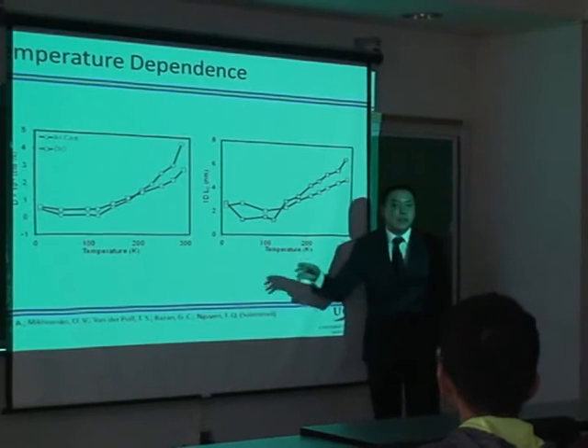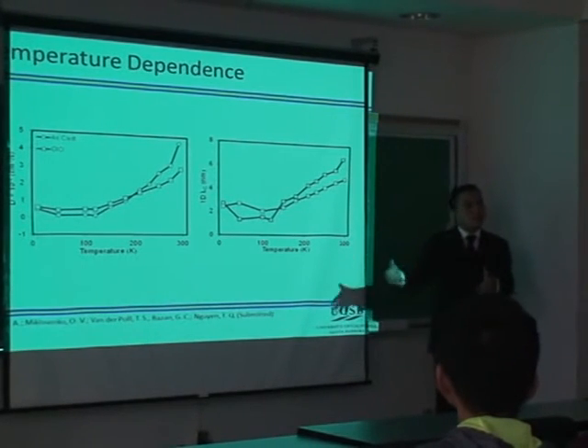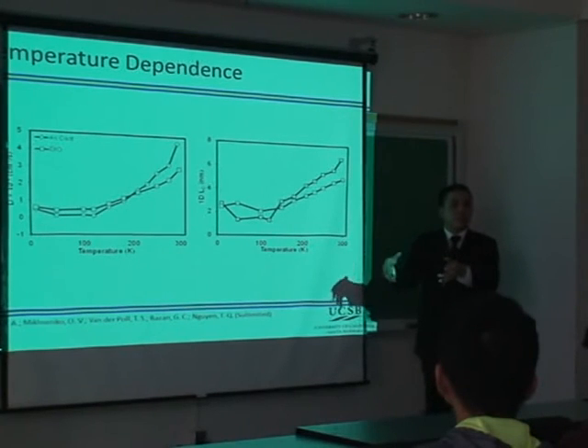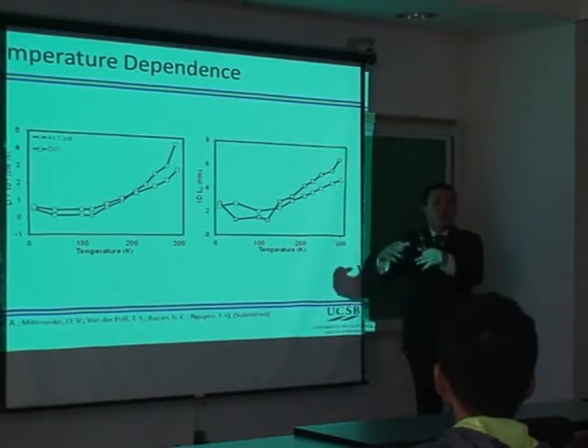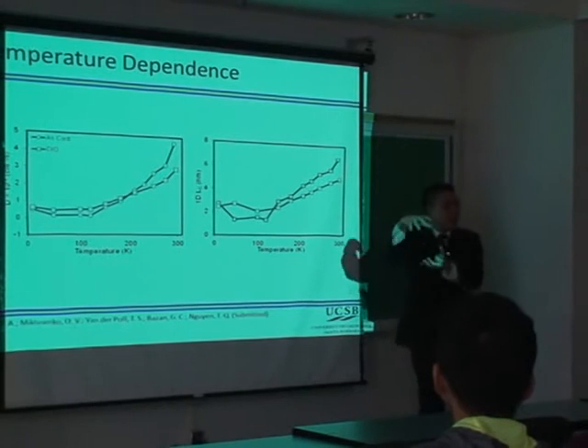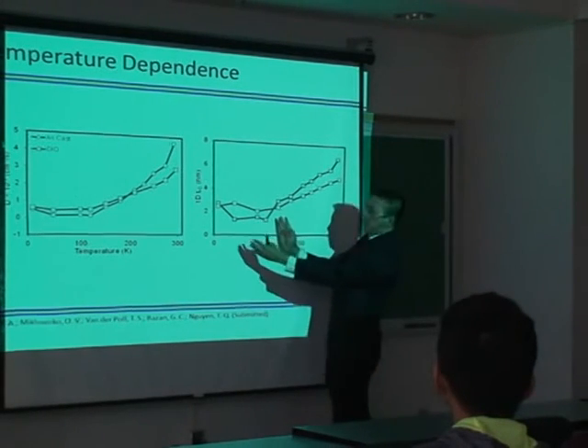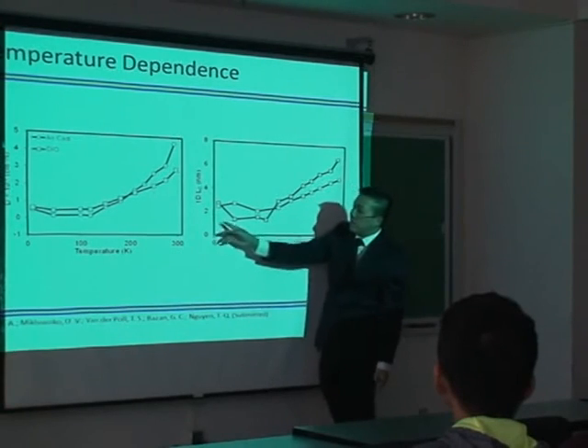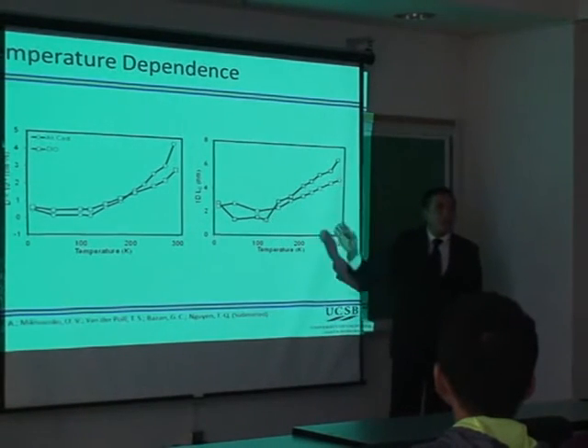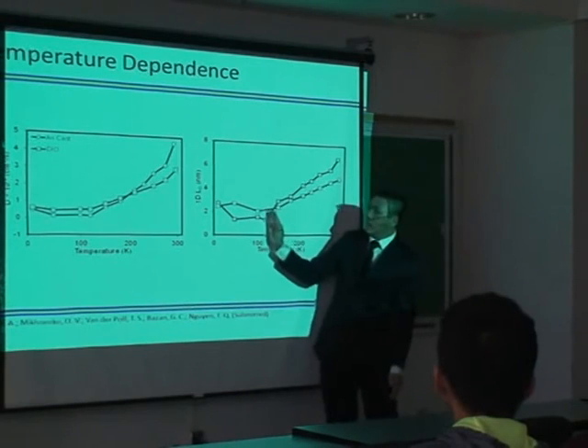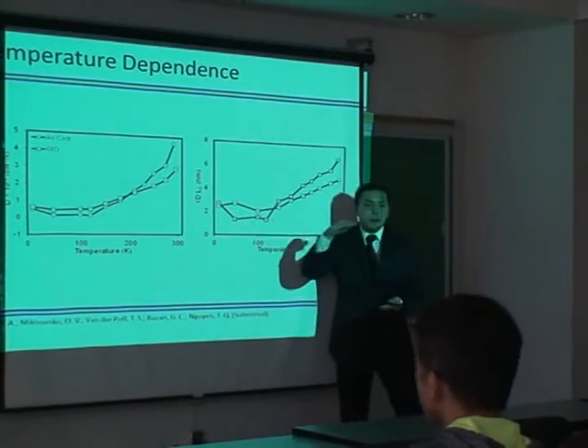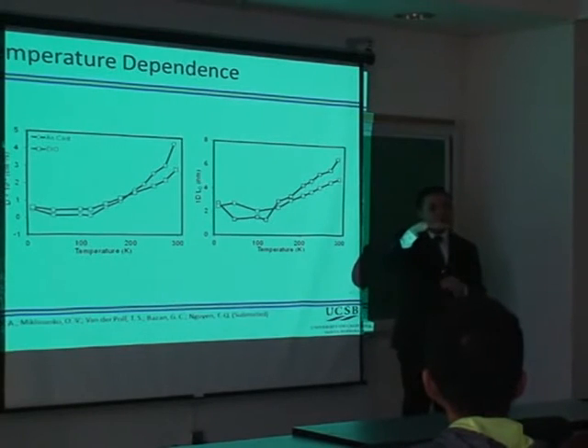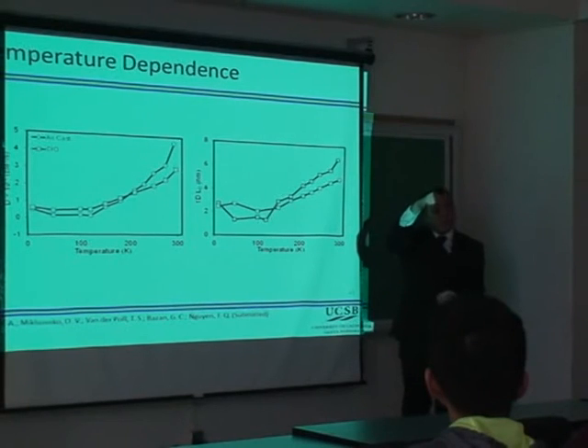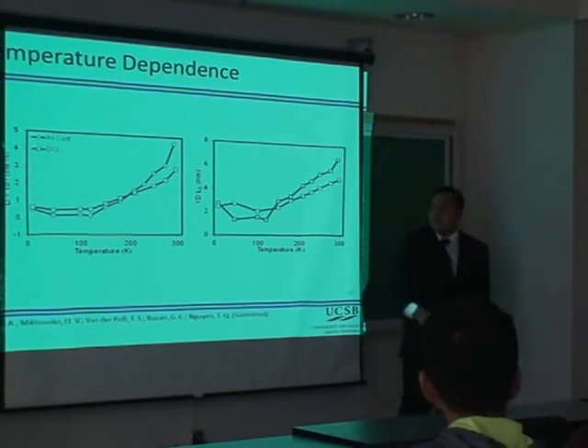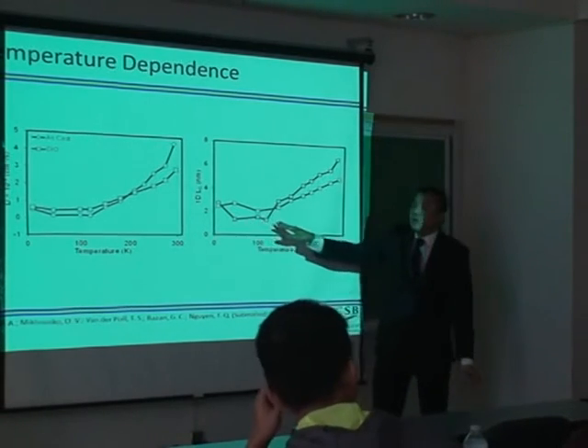What that indicates is that it confirms that the mechanism of exciton diffusion is actually temperature activated. As you increase the temperature, you increase the amount of excitons that are able to diffuse. It's a hopping process. In addition, this region down here shows that even at cold temperatures, when they don't have enough energy to hop, they can actually still diffuse. And in this region, the reason why they're able to diffuse is because these organic semiconductors actually have different energy levels. And as the exciton relaxes down, it can go through these downhill migrations and diffuse a little bit further. But it's not very much, only maybe like 2 nanometers.